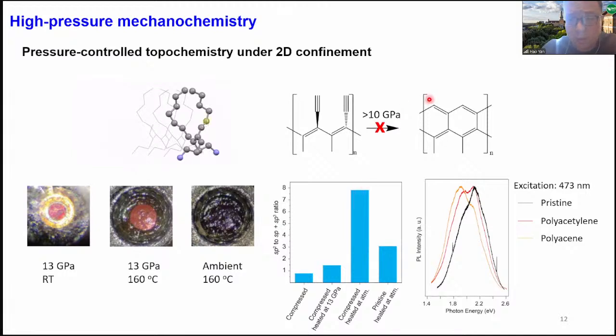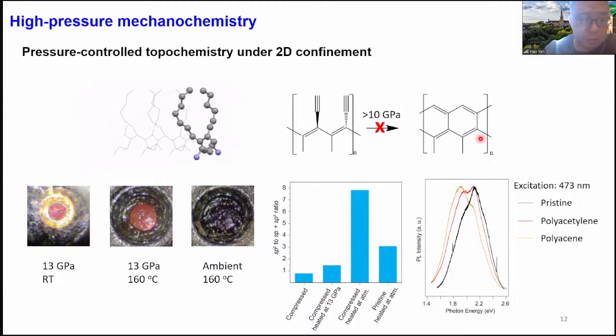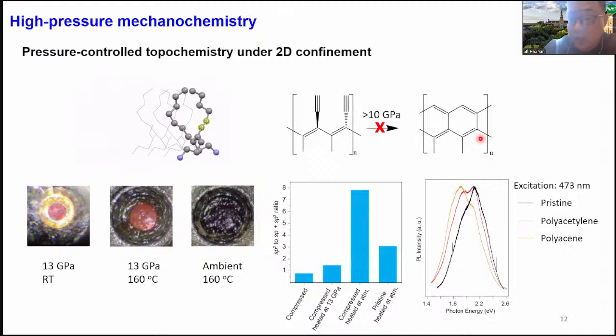Now, in order for this second polymerization to happen, these two triple bonds would have to rotate into the same plane to form this polyacene structure. And that rotation, we believe, increases the thickness of the organic layer, which goes against the pressure.